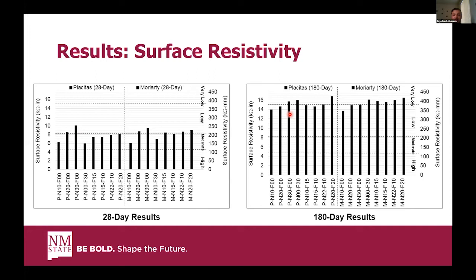But the good point here is that the later age results for surface resistivity and the chloride ion permeability for the mixtures with fly ash and mixtures with the natural pozzolan with the same percentage were very close to each other. And again, the pumicite can be a good alternative to fly ash in terms of chloride ion permeability.